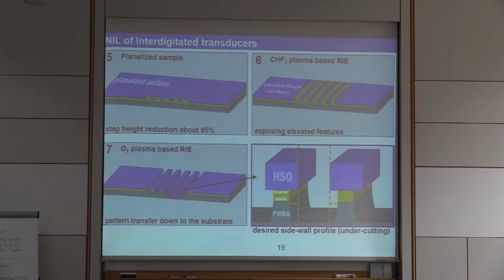Then here comes the motivation for doing this step, because once you have your features in the organic layer and you have succeeded in making this very nice and planarized, you are able to etch back the HSQ down to these organic features. So we use a fluorine-based plasma to etch back the HSQ until the moment that these features start to appear. So now you have basically a kind of silicon oxide material, this HSQ, which is in a sense inorganic, and then you have these organic features exposed.